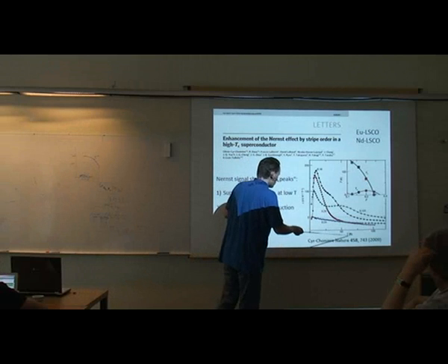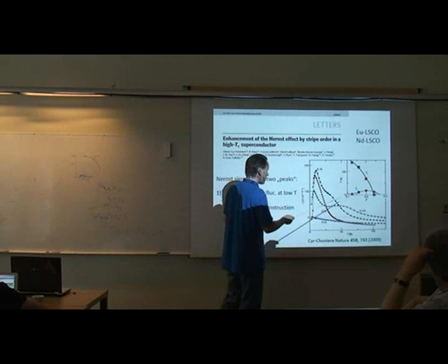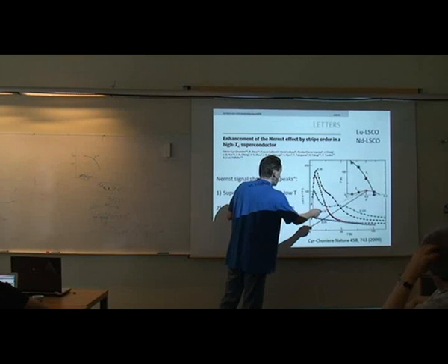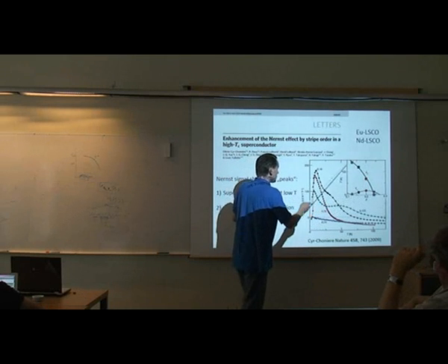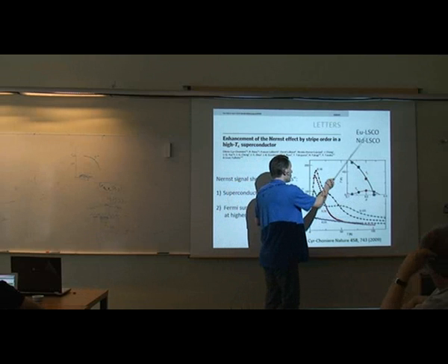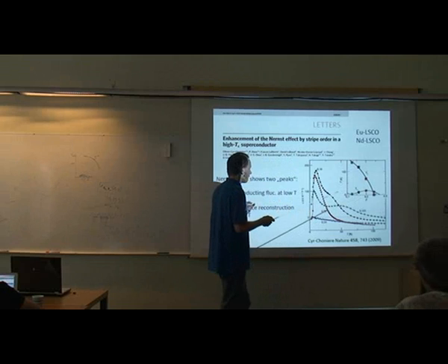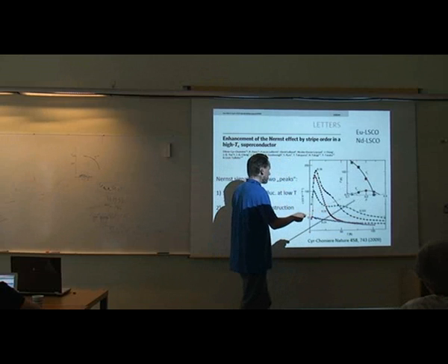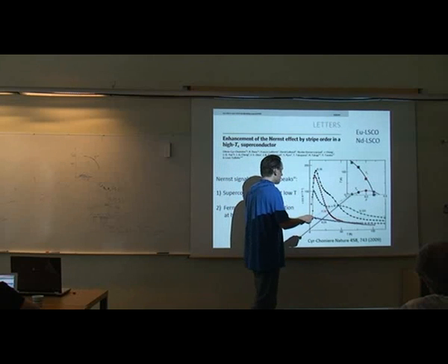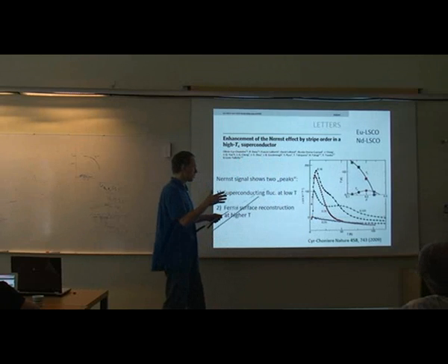And this is temperature, and you see different behavior for different data points here, here, here, and here, which is different dopings. And in this material class, where you measure this in different doping, you have different tendency of stripe order. So in this area, you have no stripe order that you see by neutron scattering, for instance, whereas here at 1/8, there's very strong stripe order with a strong local moment of the spins essentially.